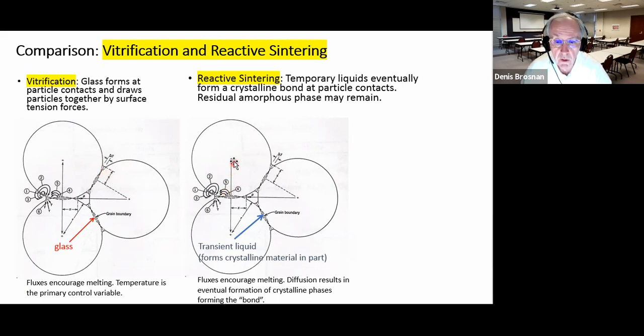Reactive sintering is different. We have the same 3 spheres in our little theoretical model of sintering here. We form some liquid, a melted phase, in the early stages of heating. But then during the process of sintering, diffusion takes place from inside the ceramic particles toward the surface. Diffusion, atom movement. Atoms move toward the surface and change the chemistry of that liquid such that new minerals are precipitated or formed by direct reaction at those points of contact. So the new minerals can become part of the bond phase. In that situation, the liquid phase may be disappearing. It could be transient in nature. Transient means it's only temporarily there, and the new minerals can form the permanent bond in the ceramic.